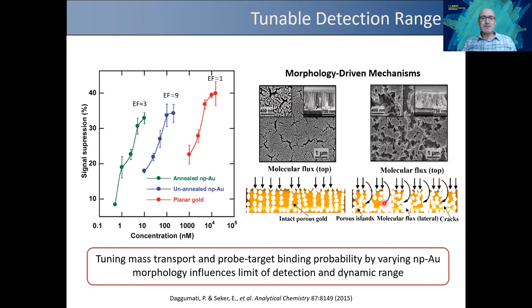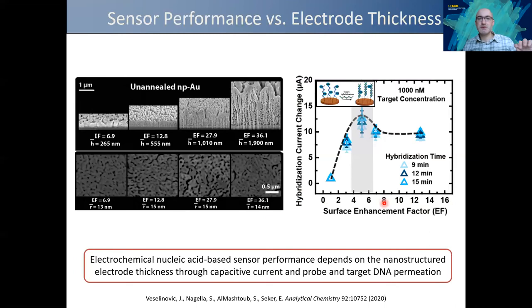So one question you might ask is, what is the influence of the thickness? You may have a really thin nanoporous gold or a thick nanoporous gold, and we wanted to study this to see if there is an optimal morphology. Because you can think of it as, if it's too thin, then it's kind of like planar gold, so the effect is lost. But if it's too thick, then you have some undesirable effects. The target needs to permeate all the way through the pores to actually capture anything.